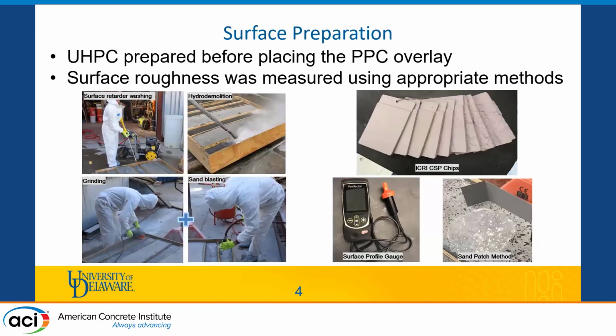To prepare each of these surfaces, we adopted 3 surface preparation methods. The first one is the use of a surface retarder, whereby after pouring the UHPC, we applied a light layer of surface retarder to delay the curing of UHPC, which was later washed off to expose the fibers. Then we also have hydrodemolition, whereby we pressure wash the UHPC surface after ensuring that it has reached the minimum 10 KSI recommended by Delaware Department of Transportation. And thirdly, we adopted grinding using a hand grinder and sandblasting to prepare the surface.